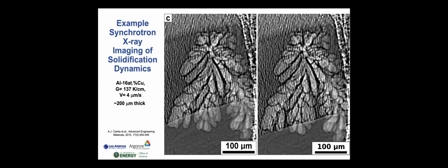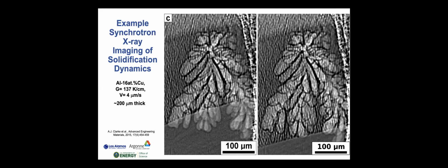And one of the real benefits of synchrotron X-ray imaging in this case is that we get really great spatial resolution on the order of about a micron or so, where we can actually resolve the lamella of the eutectic microstructure that consists of 2 different phases, in this case, an aluminum-rich phase and an Al2Cu phase as well. But really the point is we can start correlating the local processing conditions and how that relates to the microscopic structure development in metallic alloys.